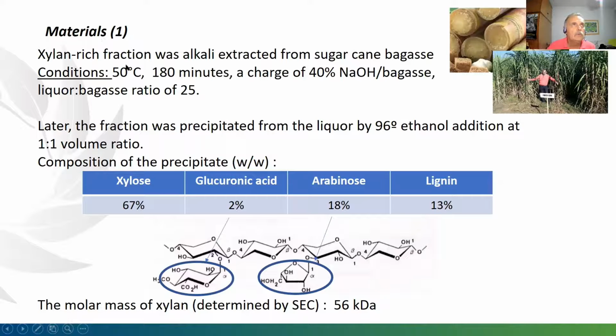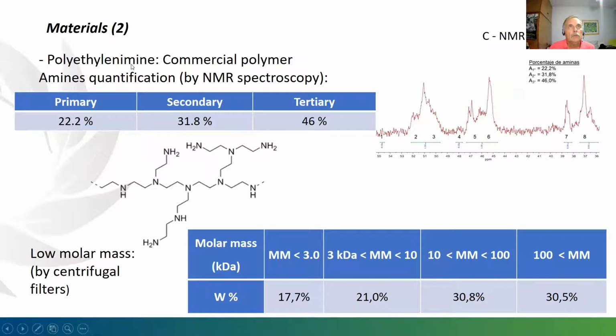We used in this work a xylan-rich fraction that was alkali extracted from sugarcane bagasse. Later, the fraction was precipitated from the liquor by ethanol addition at a 1-to-1 volume ratio. And the composition of the precipitate was 67% of xylose, 2% of glucuronic acid, and 18% of arabinose. And also, the precipitate contains 13% of lignin. The molar mass of this xylan was 56 kilodalton. And the polyethylenimine was a commercial polymer.